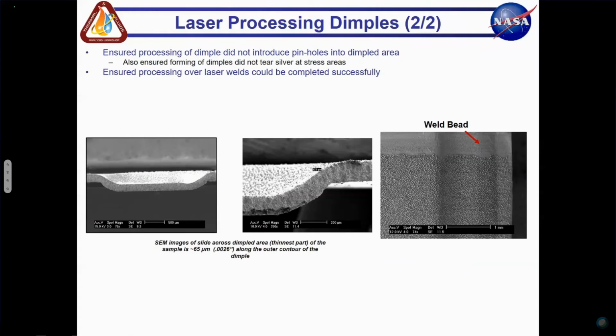What we don't want to happen is what you see in the top right picture: on the top right of that dimple, there's no laser processing. It's kind of a bare area in there. We didn't want to see that. And so we made some changes. UNL made some changes to ensure that we could process both the convex side, and the picture on the right-hand side is the negative side, so it's the concave side.